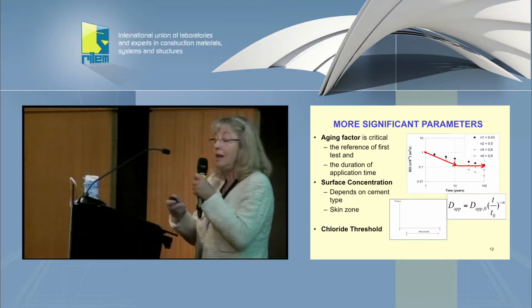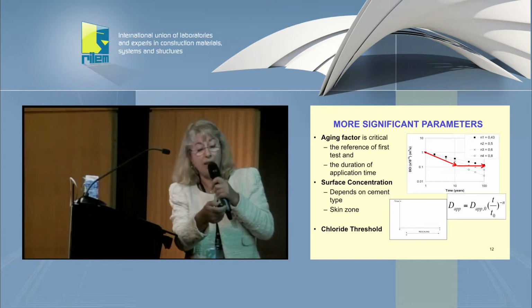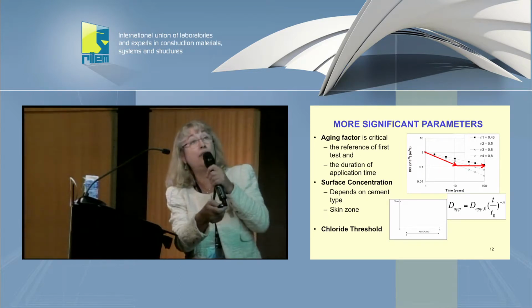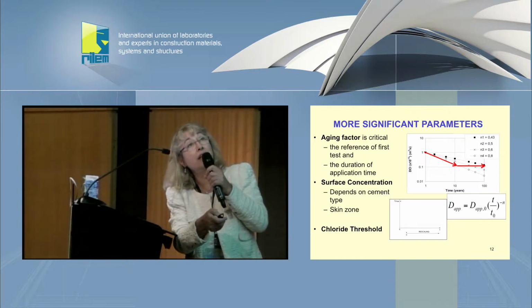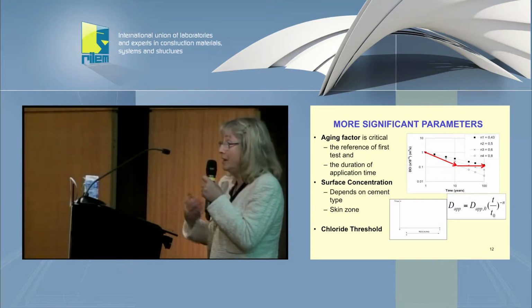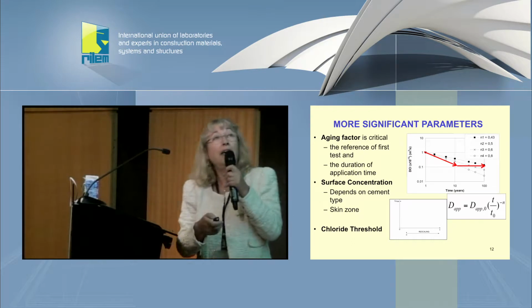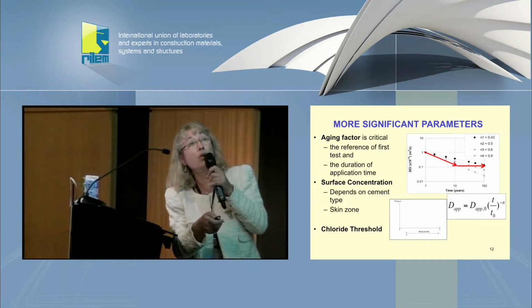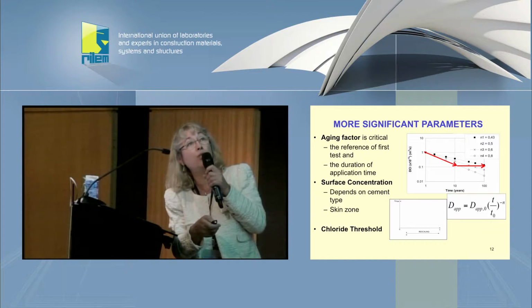We cannot leave the value to be applied during the whole life. First, because maybe it's not true, and the second, because if we go, for instance, in this case, we have almost 1 order of magnitude of decrease of the diffusion coefficient with time if we let the aging factor go until the end. If we just say only 10 years or only 5 years for the application or 1 year, that will be much more conservative, that is my recommendation, or at least less risky because of the uncertainties we have and of how this will evolve.